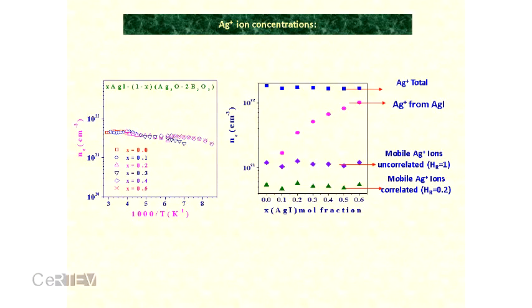Independent result, that is, activation energy is slightly dependent on temperature and also slightly dependent on glass composition. This is surprising. The charge carrier concentration is not strongly dependent on the composition. Here we have plotted the charge carrier concentration as a function of the silver iodide content, the halide salt. You can see that it is independent of temperature.